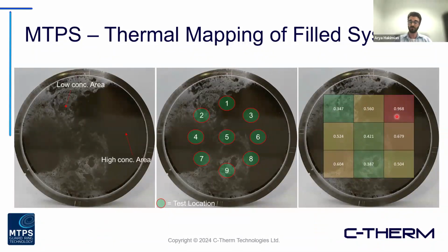So in this example, this would be a really clear case where, whether it was the process that was involved, the mixing or the curing, the end product is certainly having some issues. This is, of course, just one example, but it really gives you the ability to understand how uniform your material is. And the reason we want to make sure your sample is uniform is that if it is applied in a system where heat is being generated and we need to dissipate that heat, something inherently variable like this can lead to hot spot buildups, decreases in performance, and in some worse cases, safety issues like thermal runaway.